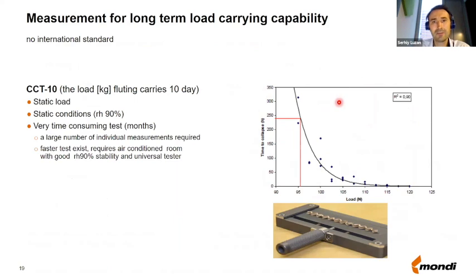So let's spend a few more minutes speaking about the creep test itself. I was telling you before about the CCT10 test, which is done at a static relative humidity condition of 90%. This test tells you what load the fluting, but it can also be the liner, can carry over 10 days. Normally you make a wave, put it in the holder under the press, load the fluting and measure the time. The final purpose is to find the relation between the load that you put on top of the fluting and the lifetime of the fluting. Once you repeat the same test for different loads, you can build this load versus lifetime relation.